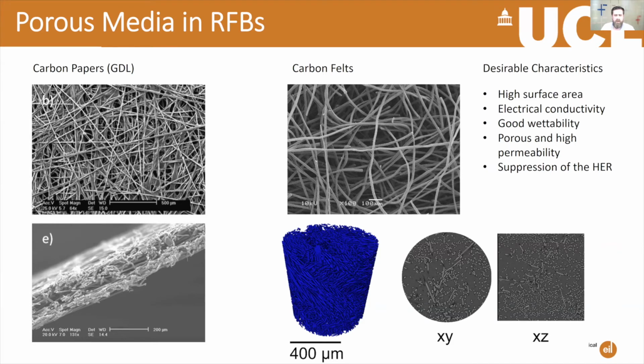So these porous media have to have a high surface area, so we can have lots of reaction taking place at any particular time. They've got to have good electrical conductivity, so we can charge and discharge efficiently. They should have good wettability for the electrolyte that you're using as well, so that you utilize the whole volume of the electrode. And of course, they've got to be porous and also highly permeable, because when you're pumping the electrolyte through these materials, if you have low permeability, you're going to have a larger amount of parasitic pumping losses. So you actually use a lot of your power in pumping the electrolytes around. In the case of aqueous electrolytes as well, it's quite important on the negative electrode to suppress the hydrogen evolution reaction.